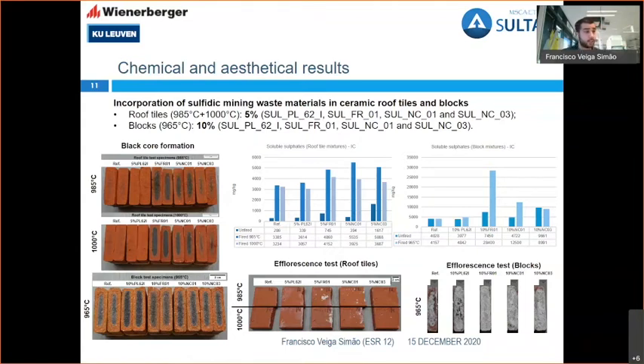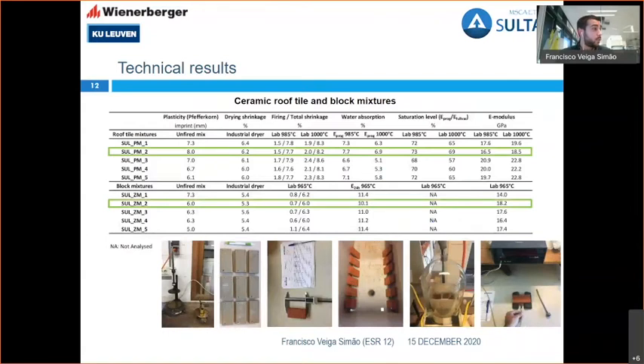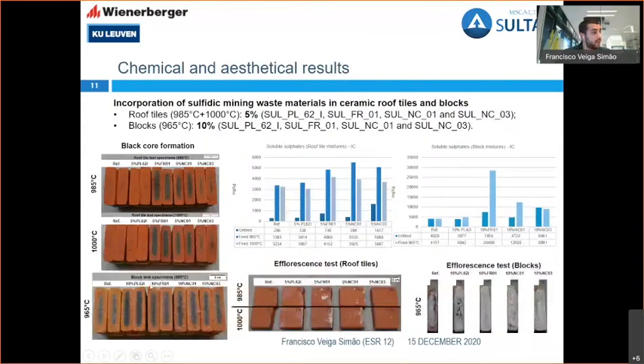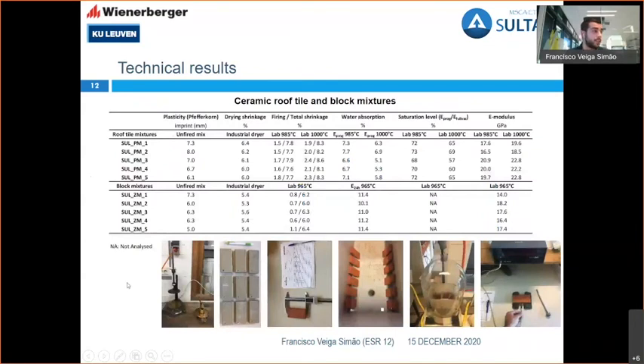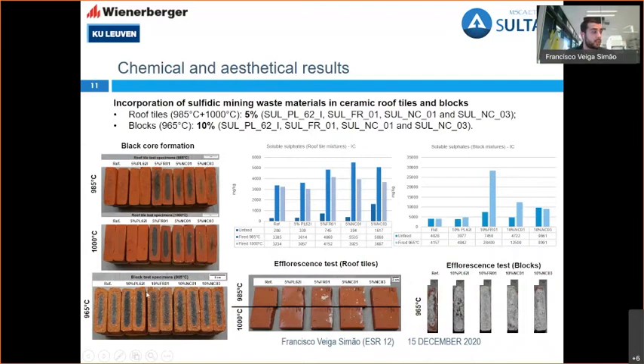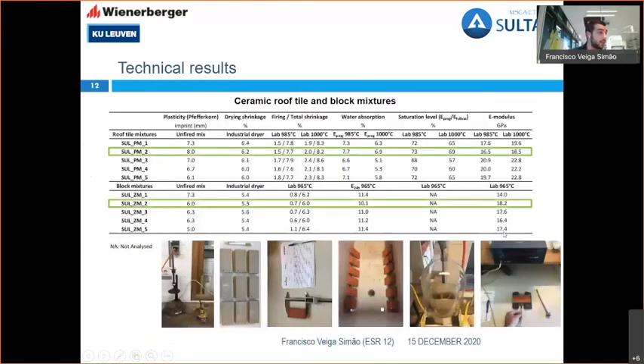On the technical results, it was concluded that indeed the Plombières is the most similar to the reference. In some cases for the blocks, it even increases the strength, the modulus of elasticity, the E modulus, which means also that there is a more denoted black core from all of them, which also increases the strength. There is a straight link between these iron oxides that get trapped during the sintering process and the increase in strength. Moreover, more tests were also done on the technical side, also the water absorption under progressive and vacuum conditions, and also the modulus test by a non-destructive method.